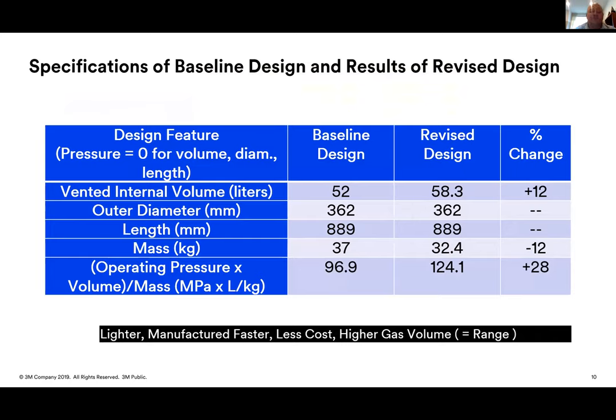This is the result in more detail. You see that the vented internal volume can increase. You're taking the weight down, and this improves the efficiency. While you're doing this, you're making a lighter weight tank that is manufactured faster. It costs less because you're removing fiber, and you're increasing the gas volume, which actually improves range.